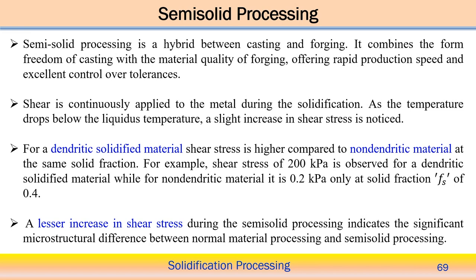So here you can say that it combines the freedom of the casting with the material quality of the forging process. Combining these two, casting and forging operation, rapid production speed is possible here, and of course excellent control over the tolerance. Tolerance levels can be very precisely controlled in semi-solid processing techniques, because even for the casting process we need to account for shrinkage, and shrinkage may happen at one particular position, such that the volumetric shape will change to accommodate the shrinkage volume. Even a riser is needed to accommodate the shrinkage volume in the case of pure casting operation.